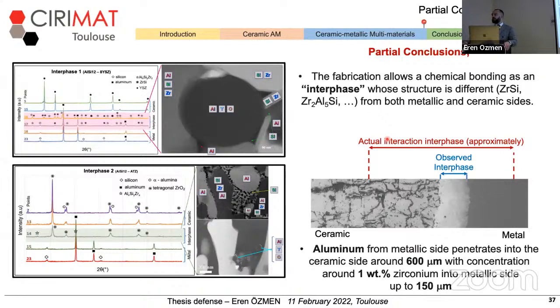So if we want to conclude this second part, the multimaterial part, we can see that a chemical interaction and bonding between the metallic and ceramic part is created because we observed an interface. This interface has a different composition, including a ternary phase and intermetallic phase, and it's different from both metal and ceramic parts. Also, one important outcome from this part was that the interface, the interaction zone, is larger than what is observed with some images, because we see that aluminum can be detected in the ceramic part up to 600 micron in the first combination, and up to 300 micron in the second combination.